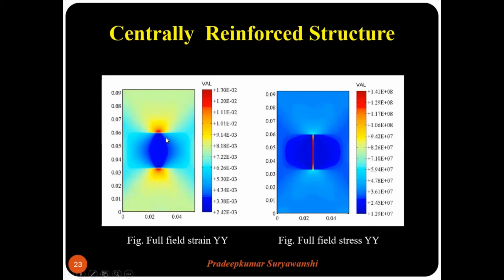If you look at the full field strain here, we can see there is a drastic reduction in strain in the inclusion, shown by clear blue. Near the tip we can see the maximum value of the strain. That means deformations are very high in this area near the tip. These are the areas where there is a chance of nucleation of a crack, which may propagate in the matrix. So at the tip of the reinforcement there is a strain concentration, and these are likely places where a crack may initiate and propagate in the matrix. In this diagram, we can clearly see the purpose of reinforcement: it takes up the complete load, and the stress in the matrix is blue, which is very low compared to the red values in the reinforcement. Our MSS model properly predicts these results, and all these results are in line with the results presented in the literature.